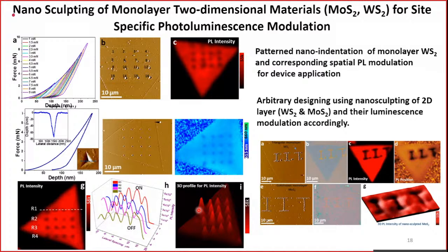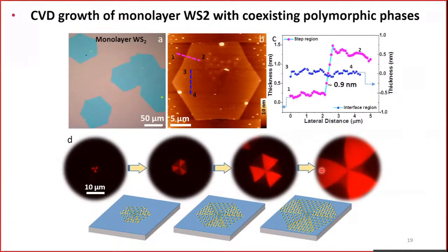Then again, we can clearly see that the PL, the optical signal, can be modulated based on the pattern that we draw. These are some of the examples where we have written IIT by the nano indentation. Accordingly, you can see in the fluorescence imaging and PL mapping, the optical emissions can be easily manipulated.